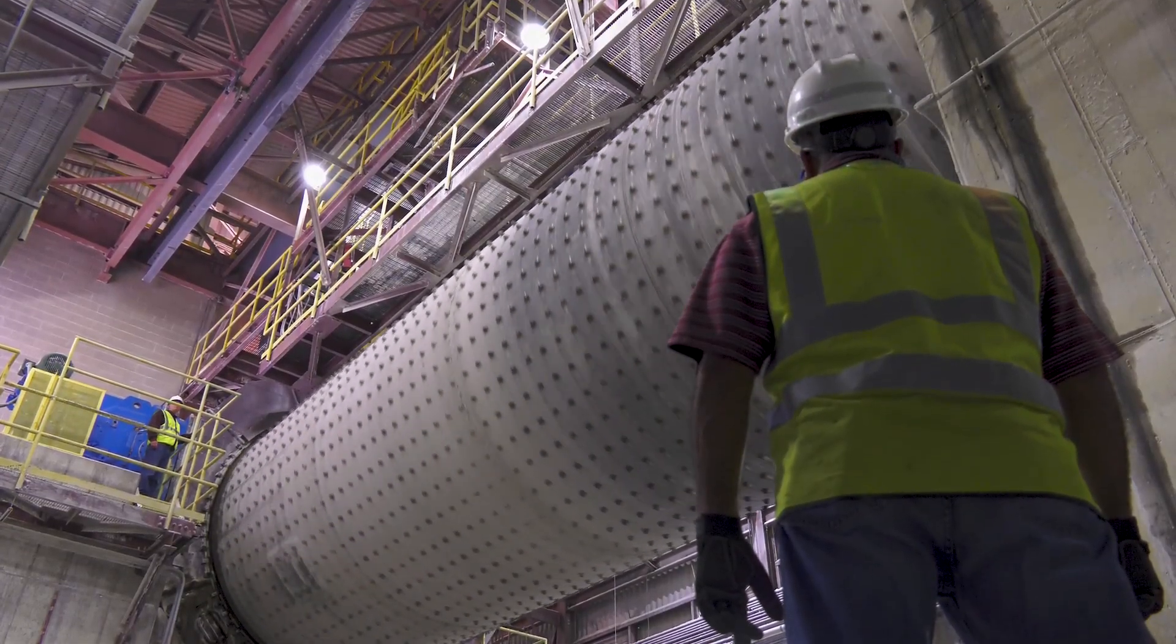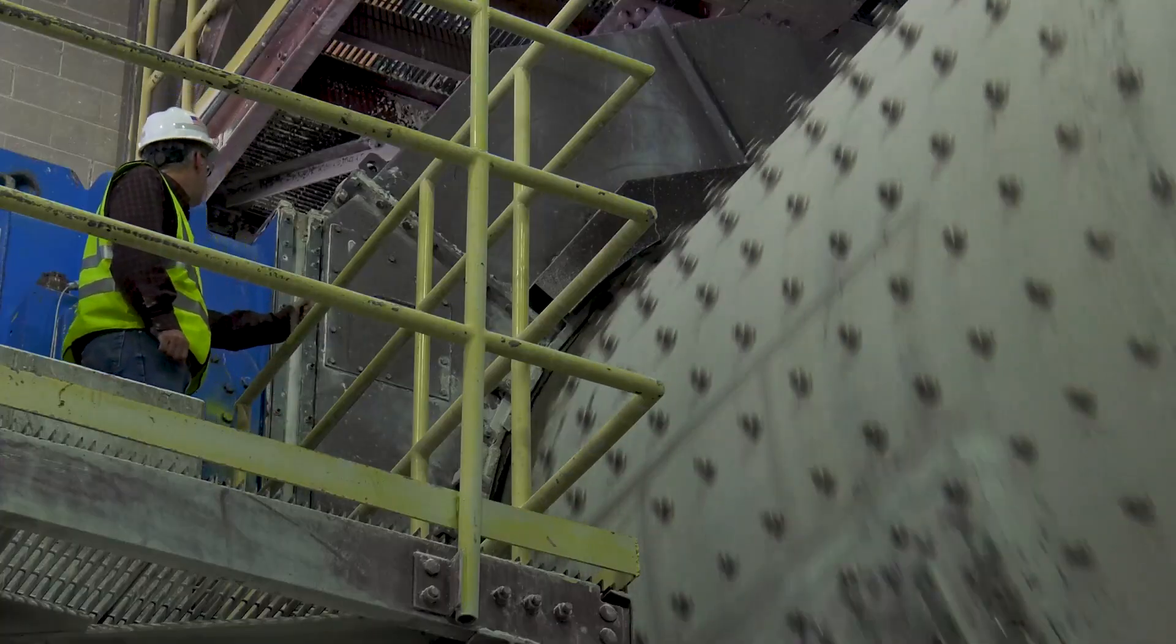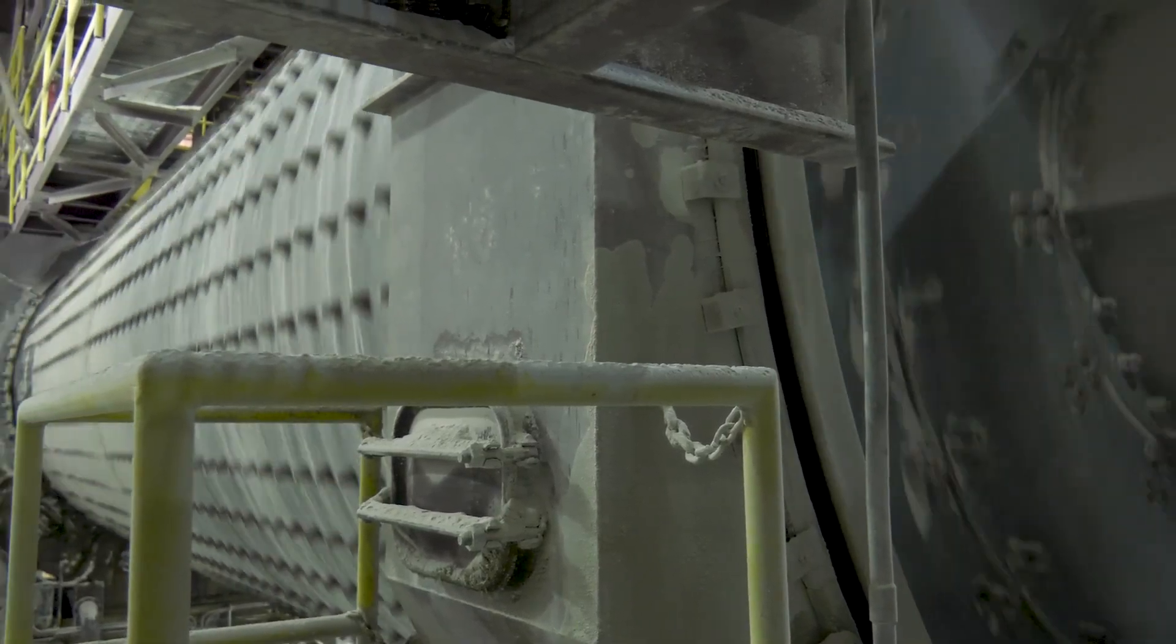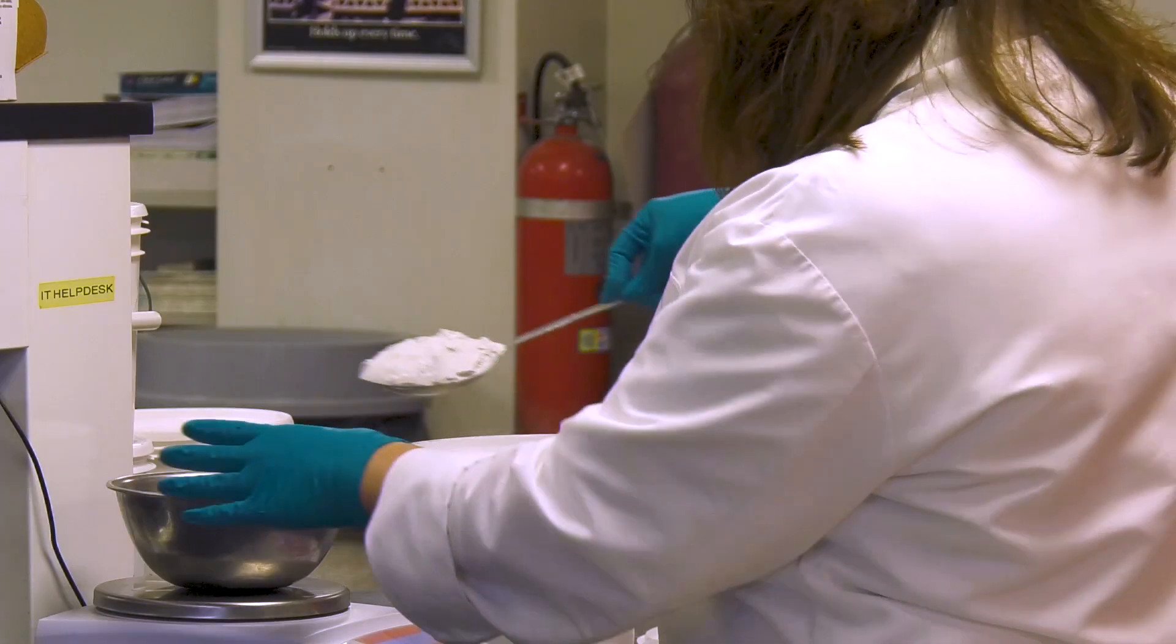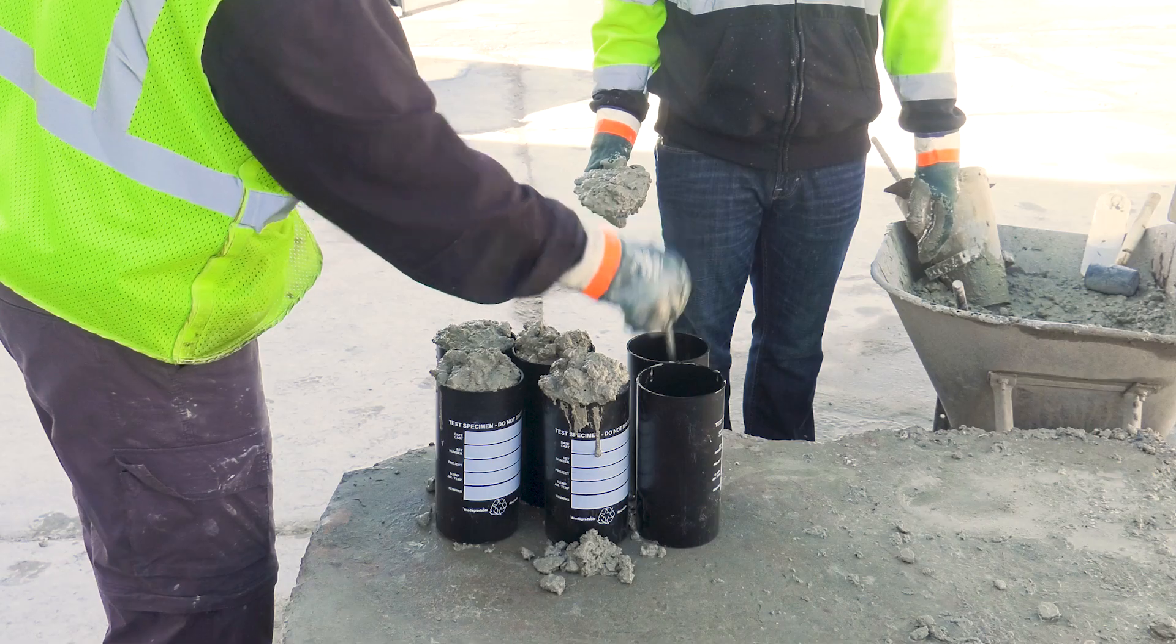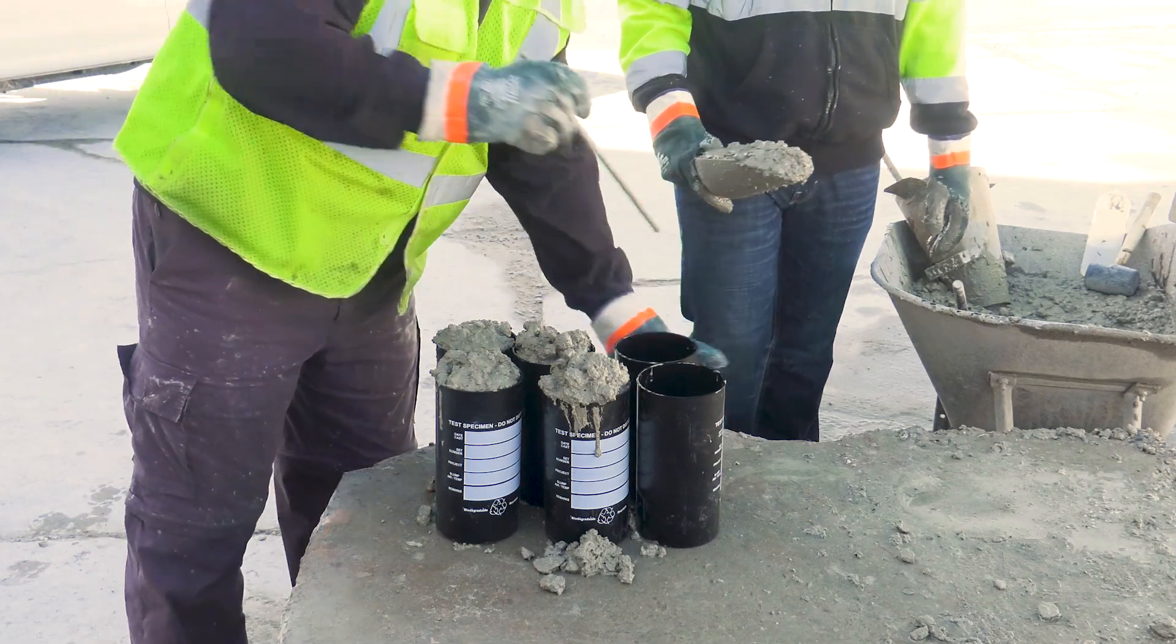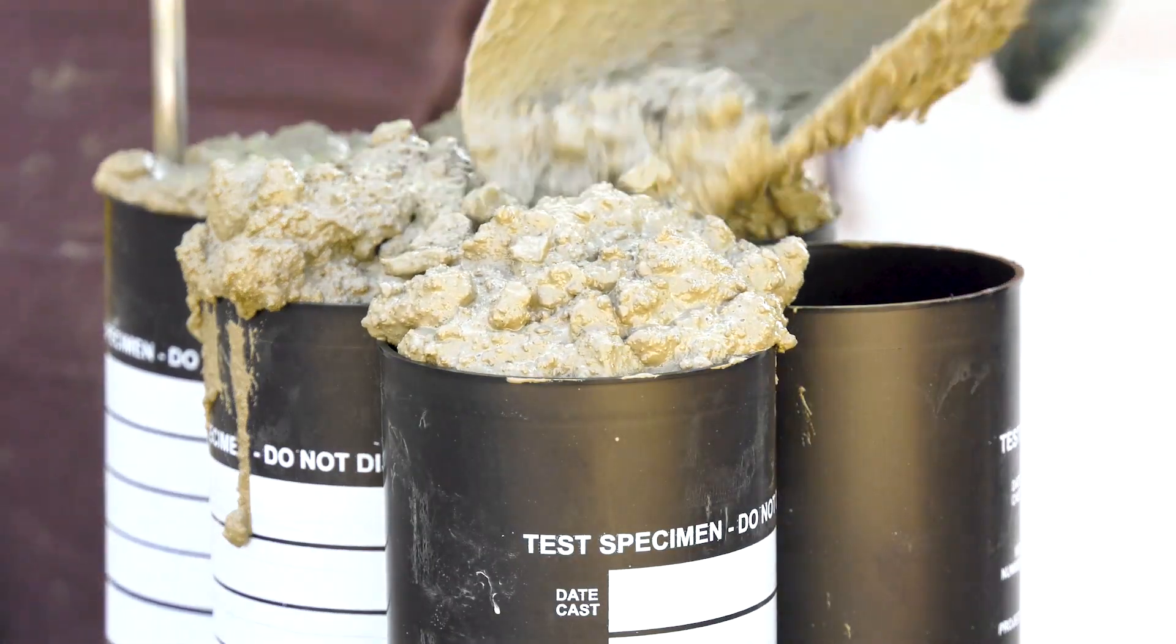Gypsum also facilitates the grinding by preventing clumping and coating of the powder at the surface of the ball mill wall. At that point, it makes its way into the ball mill, which is our finished part of the grinding process, and then essentially into a separator which classifies the material and determines whether it's fine enough to make it as a finished product or it needs to be reground through the circuit again. The grinding process is controlled to obtain a powder with the desired amount of fineness. The rate of initial reaction of the cement when mixed with water is directly proportional to the fineness of the cement.